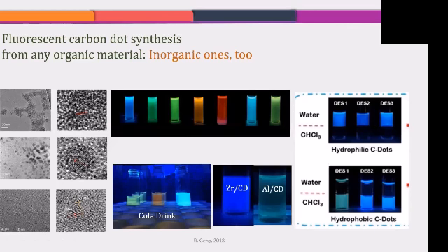But then researchers found out that depending on the size, crystal structure, and especially doping, if you change the surface properties by doping with amine groups, carboxylate or sulfur groups, or if you add new metals onto the surface, you may change the color of the carbon dots. You see that there is no difference in the colors from the semiconductive quantum dots made from heavy metals, and their quantum yield has already reached the same level.